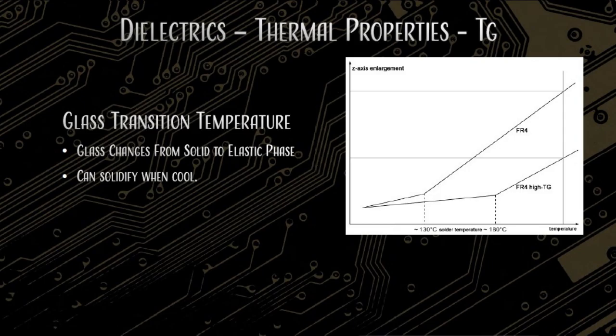All right, so glass transition temperature, Tg, is the temperature at which the fiberglass goes from a solid, strong material to a rubbery concoction, think of it like silly putty. It's the temperature at which this stuff starts to move from solid to liquid. It's not liquid, it's just a really amorphous solid. It can be moved around a little bit. The issue is that when you're trying to assemble your board, if you've got a low Tg, your board can actually start to warp and bend while it's going through the reflow ovens, and that can be bad. So Tg is something you often want to look for, especially when doing RoHS compliant, lead-free solder. That's just one of the many jargon terms that we have.